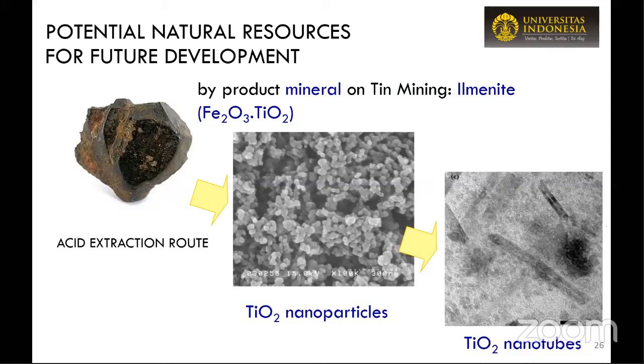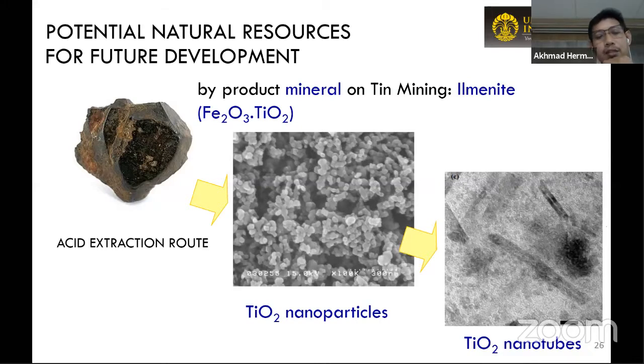I think the distribution of the size is quite uniform. And actually, there is one promising improvement. Besides the nanoparticles in spherical form itself, we can find this kind of thing, the nanotubes. So this is one fact, that we can provide TiO2 nanotubes from our own local mineral.